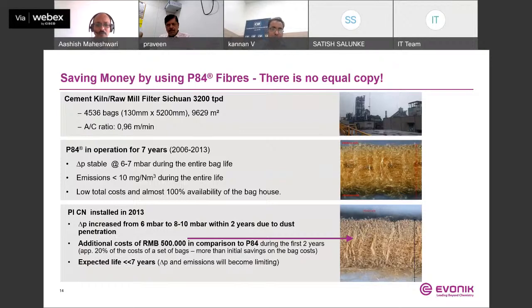Because of the PI CN fibre, the DP increased from 6 millibar to 8 to 10 millibar, and within 2 years dust had penetrated. That additionally increased the cost as compared to the P84, and the expected bag life also drastically reduced as compared to the 7 years.